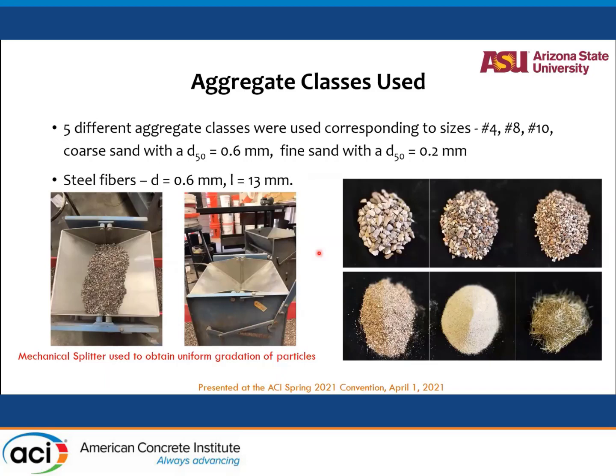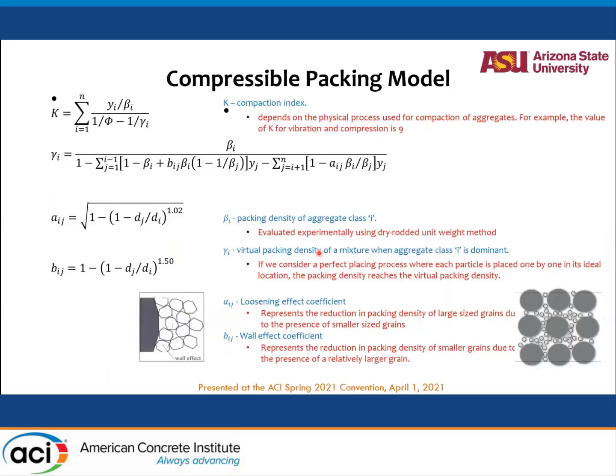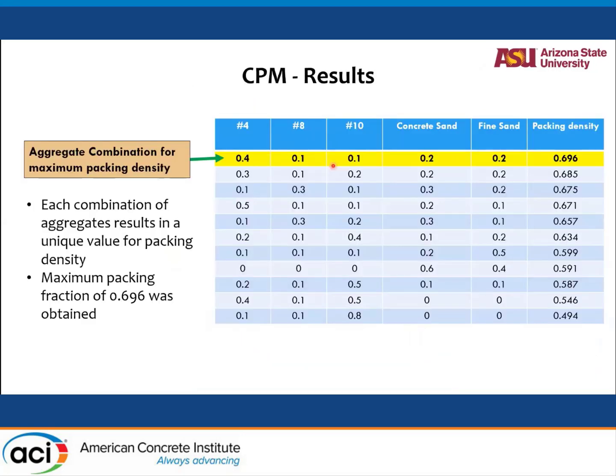We used a compressible packing model. I'm not going to get to the details of the model. Basically, we define a compaction index and develop the packing factors for each class of aggregates, beta i's, and then based on the virtual packing density, which you can obtain from the packing density of each class that you can obtain from your dry rodded densities, and some correction factors for loosening, wall effect, etc. You come up with a packing model, and we came up with hundreds of different theoretical combinations based on the experiments that we had, and each combination results in a unique packing value.